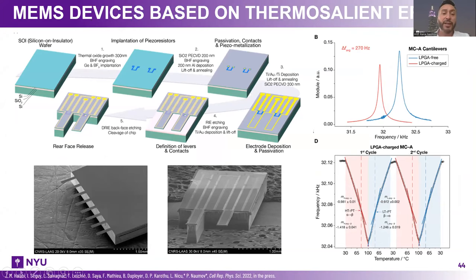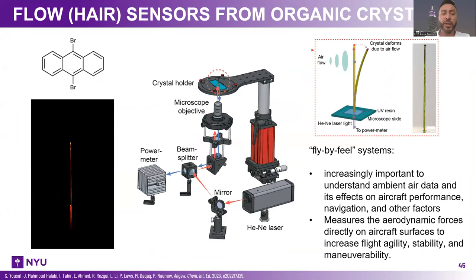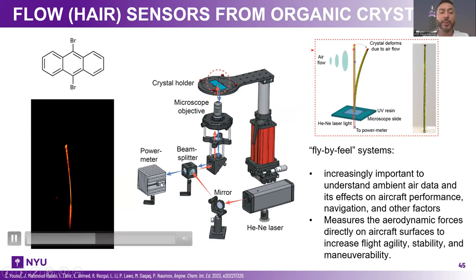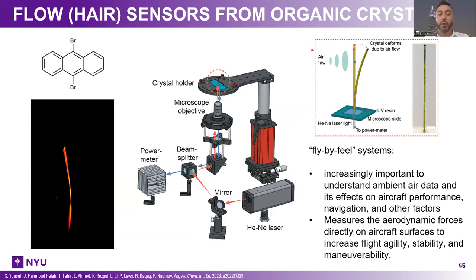One other example that I had to mention here is the so-called flow sensors or hair sensors. These are sensors where we have basically a single crystal which has been stamped with a fluorescence dye on top of it. We pass light through it and we measure the fluorescence that comes back from the crystal. When we put a flow of air, nitrogen or any gas, this crystal is deformed and we have a change in the intensity of the light that we receive back. So we can make a calibration curve and use this system to measure the flow of the air.